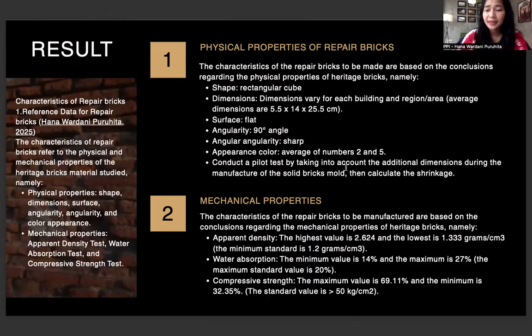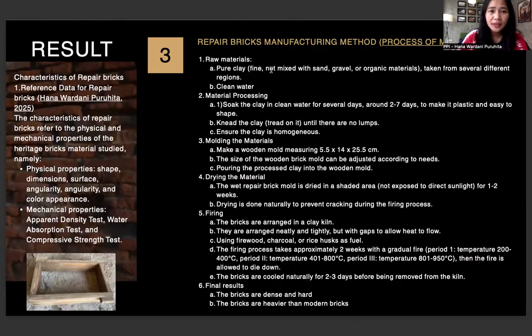2.6 and 1.3. And then the result of number 3, the process of methods. Raw materials: pure clay, and then clean water. Material processing: soak the clay in clean water for several days, and etc. Molding the materials, drying the materials, firing the materials, and final results.